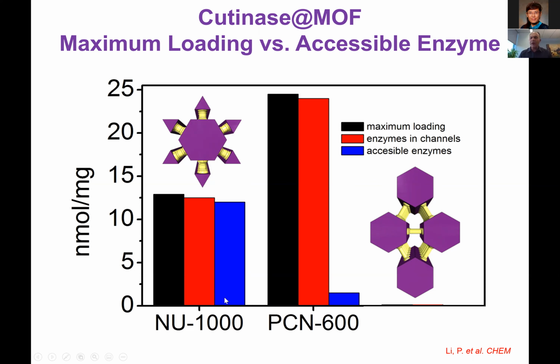The blue is almost 95% or more of the enzymes are accessible, versus if you only have hexagons and no triangles, only less than 10% of these enzymes are accessible. That means only the enzyme by the windows that the molecule can reach are active and accessible. The rest of them in the channel, we cannot reach them. So in this case, it doesn't matter how much enzyme we could put, we cannot really reach.